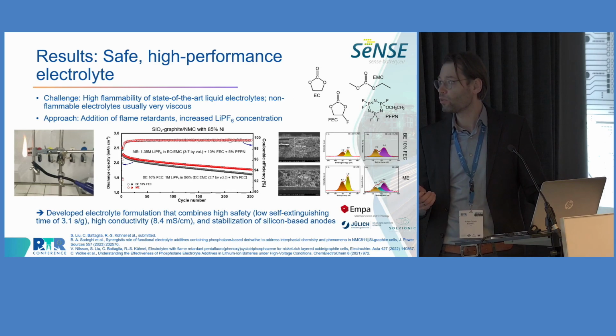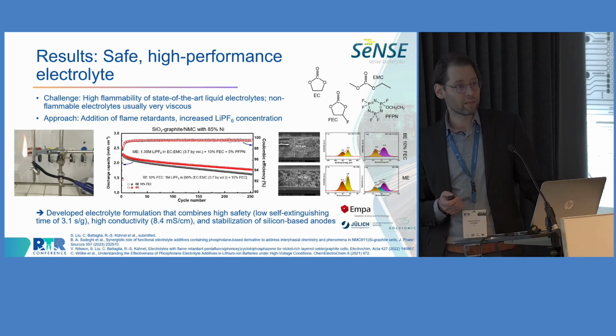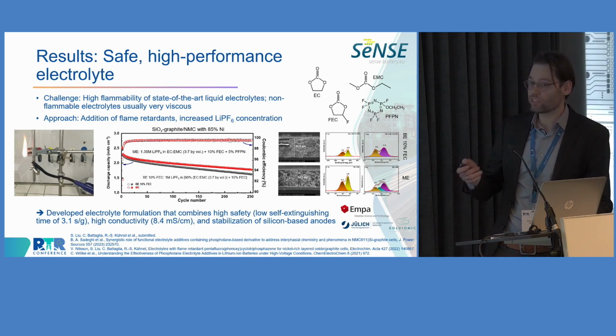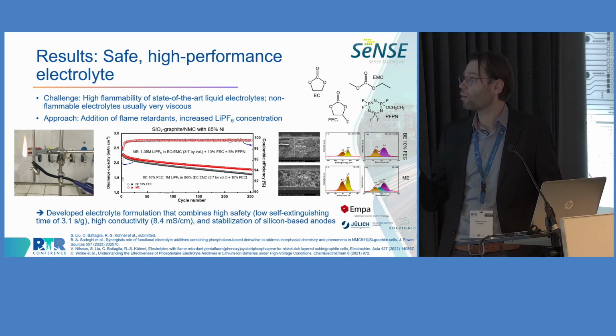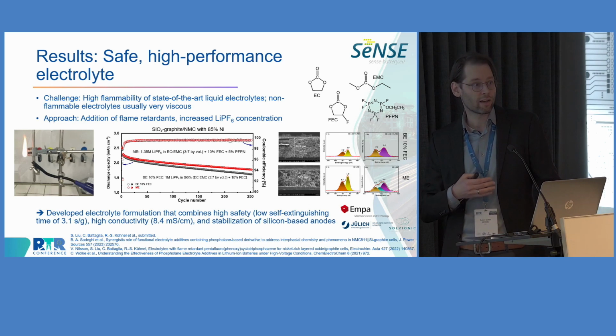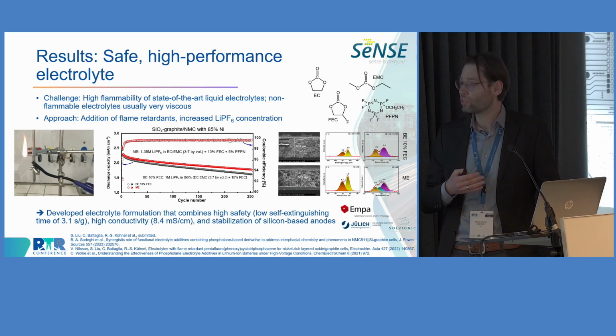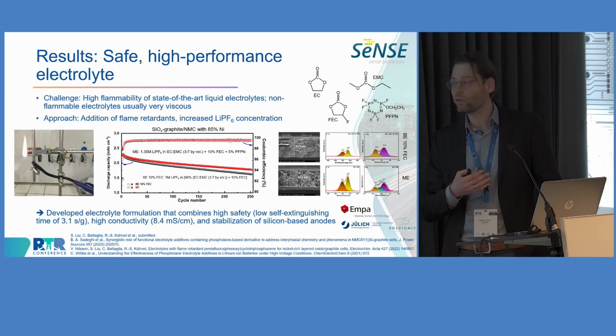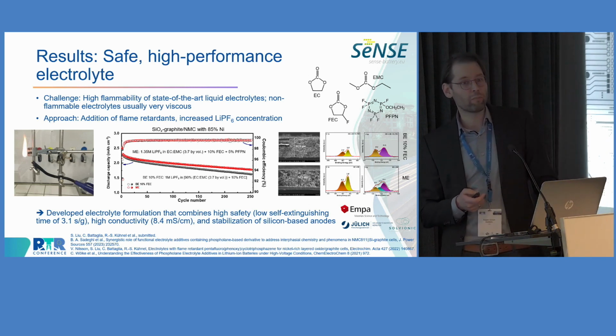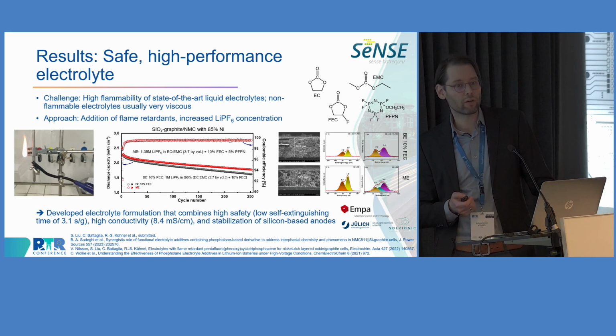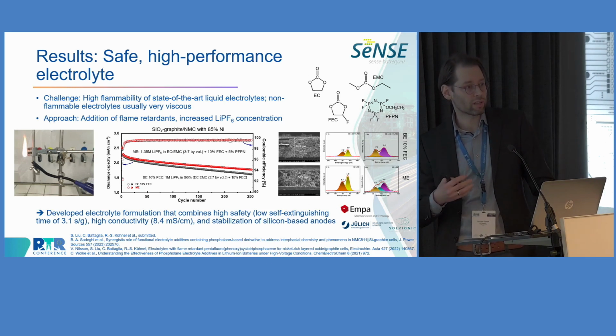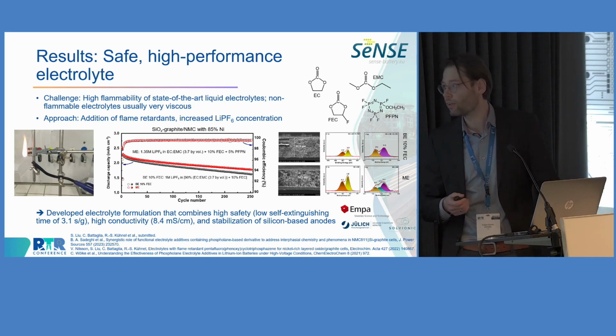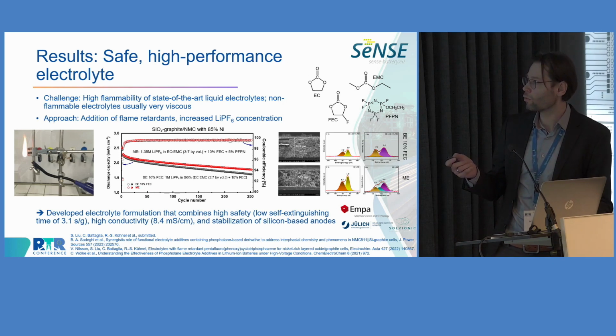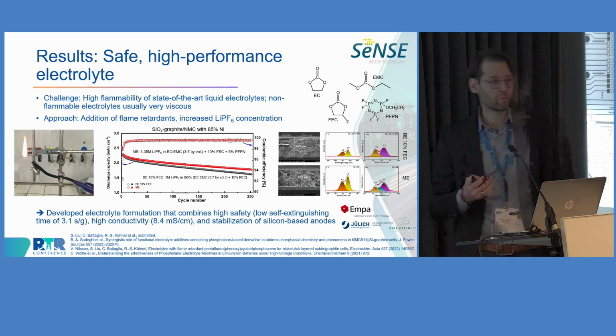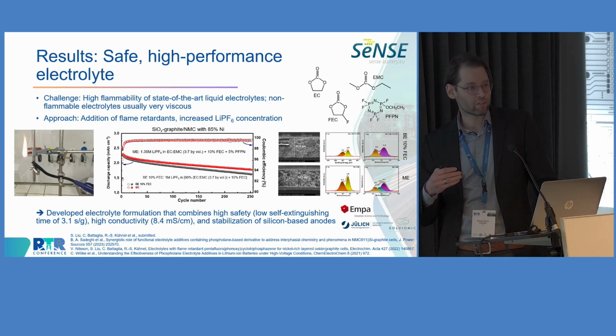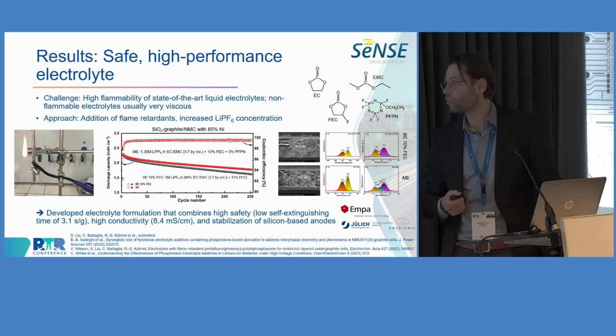The second example I would like to highlight today is about an electrolyte that we developed in the project. So state-of-the-art liquid electrolytes for lithium-ion batteries are based on these carbonate solvents, and especially the linear carbonates are highly flammable. So we were looking for strategies to reduce the flammability of the electrolyte in order to improve the safety of the battery. And there are, of course, multiple approaches, but many of the existing approaches come at the cost of very high viscosity, meaning very low conductivity of the electrolyte, which is then detrimental for the power performance of the cell. So we explored multiple approaches in this project, and one approach that turned out to be quite successful is the use of flame retardants, because when we add flame retardants, we don't have to add that much, so the penalty in terms of conductivity is not that large as compared to some other approaches.